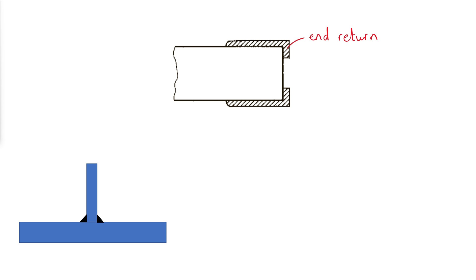Small welds are generally cheaper than large welds. The maximum size that can be made with a single pass of the electrode is approximately 5/16 inches and multiple passes will add to the cost. In addition, for a given load capacity, although a small weld must be made longer, a larger and shorter weld will require more volume of weld metal. Reducing the volume of weld metal will also minimize heat buildup and residual stresses.